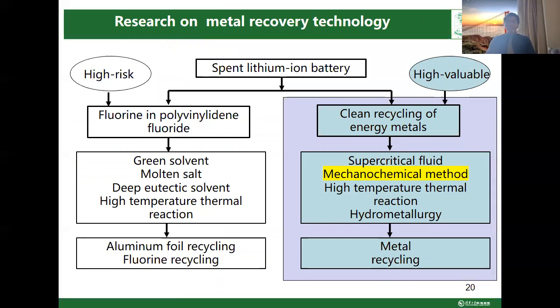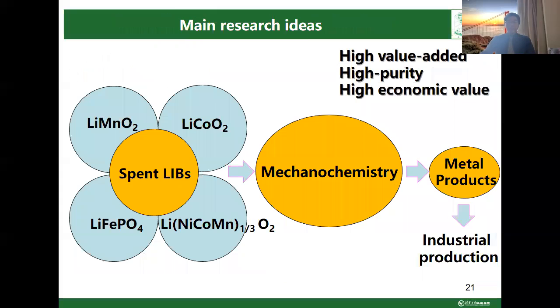Regarding the recovery of valuable material in spent lithium batteries, in order to resolve the technology defects of the traditional recycling process, we have designed a series of environment-friendly recycling processes for valuable metal in spent lithium ion batteries using emerging technologies such as the mechanochemical method. According to the type of cathode material, spent lithium ion batteries can be divided into lithium iron phosphate, ternary nickel cobalt manganese, lithium manganate, and lithium cobalt oxide. Our idea is to dismantle the spent lithium ion battery first and then obtain the cathode material powder.